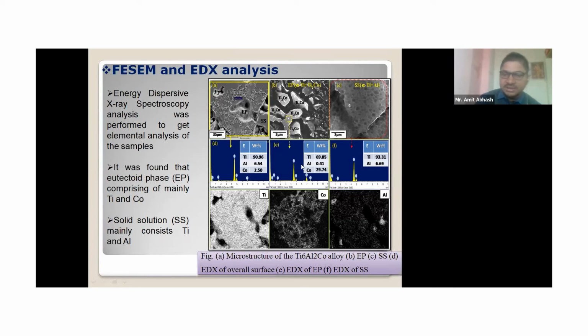This is the elemental mapping of the Ti6Al2Co part. We have to confirm whether this is Ti6Al2Co or not. So we did the EDX analysis, and found 69.85% of titanium and a very negligible amount, 0.41, of aluminum, and cobalt. We can see the major portion is titanium and cobalt, with aluminum approximately tending to 0.